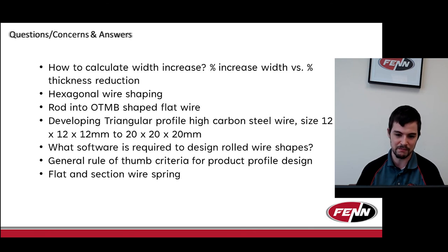Which goes to talking a little more on the width side. The typical rule of thumb is that, with the exception of the first pass where I can go beyond that, depending on what you want to finish width and thickness wise, in terms of your width to thickness ratio, if you're starting with round, I usually dictate that you can roughly double your width with each consecutive stand in the line until you get to as flat as possible, roughly speaking. So if you need an 8-to-1 width to thickness ratio, depending on the tensiles of your material, it would be roughly 3 stands.